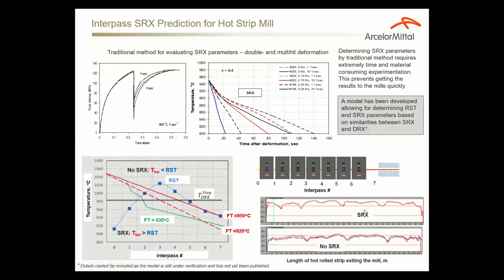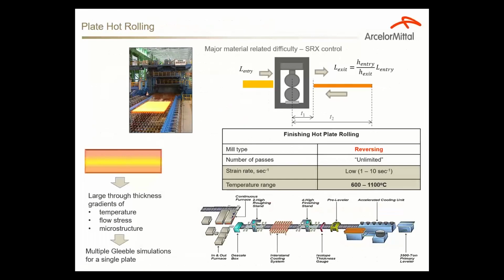These are two actual temperature profiles at the exit of the hot strip mill. And you can see that lowering the finishing temperature can help avoid recrystallization before transformation starts. So this is the kind of information we're still working on, but we're giving the mills at least the estimate for thermomechanical processing for no recrystallization thermomechanical process.